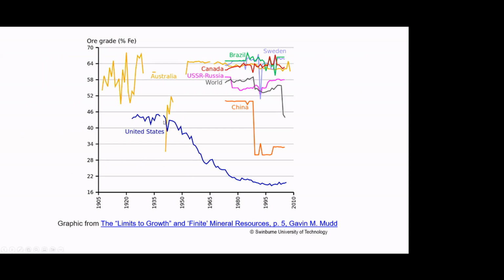In the United States, they use an ore called taconite, which they have to refine before it even goes to the blast furnace. It's a very low iron grade, and they have to carry out a lot of beneficiation. That's what's used in the United States, and that's one reason why the United States is one of the best recyclers of scrap steel, because their ore grades are so poor. The largest exporter of iron ore is Australia, and as you can see, the ore grades tend to be below what is required for hydrogen steelmaking. So this is quite a problem.